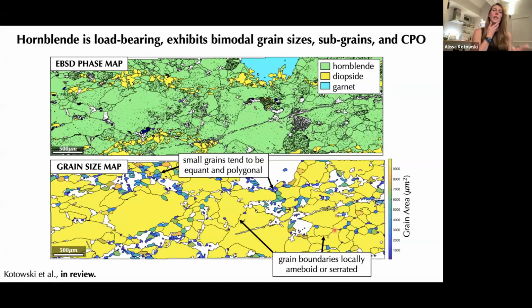So with EBSD, what we're able to do is map out the types of minerals that are in the rock, their spatial distributions. We can measure things like grain size. We can look at grain boundary and phase boundary morphology. We can quantify crystallographic preferred orientation, and we can look inside minerals as well and look at patterns of intracrystalline plastic strain. So with all of these observations, we're able to make an interpretation regarding deformation mechanism, and this is fundamental to understanding this rock's rheology.